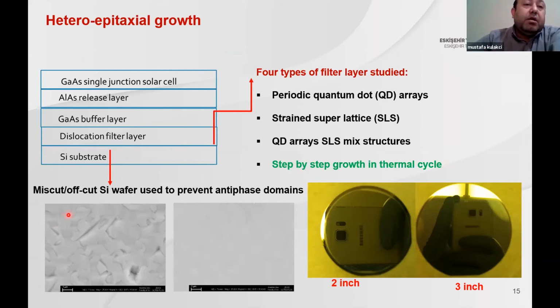Here you see these wafers are grown on 100 silicon wafers, but they end up with anti-phase domains, like a multicrystalline silicon solar cell, due to gallium anti-site bonding between gallium and arsenide levels. But by changing the template to a miscut, off-cut template from 100 by 4 degrees, we prevent this APD formation. Here you see two of our growth structures over 2-inch silicon and 3-inch silicon. It's just like a mirror-like reflectivity over the surface.